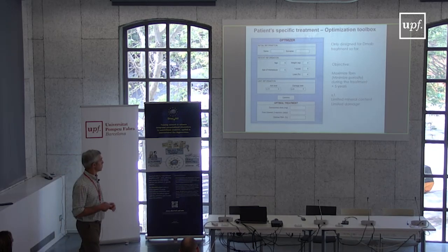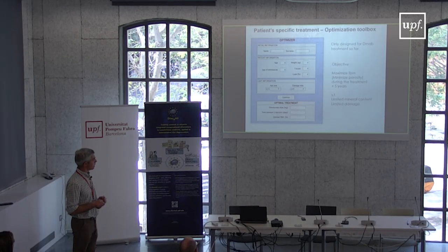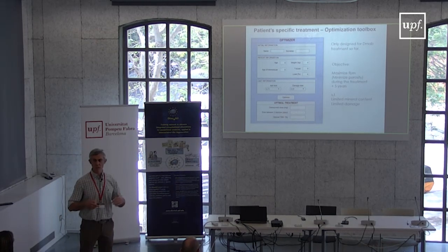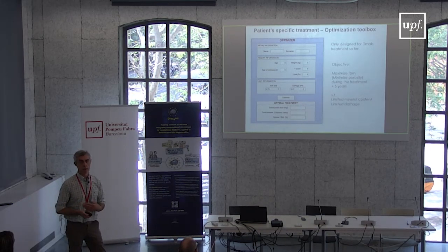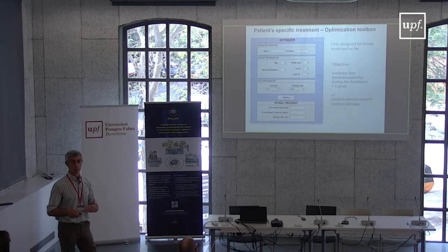So we want to include an optimization tool in our model. That's why we want to use it not just as a calculator, but also as an optimizer. The objective would be to maximize the bone volume or to minimize porosity, subject to different conditions. For example, a limited mineral content, because an excess of mineral content would fragilize bone matrix, or we want to limit damage in order to reduce fracture risk as well.